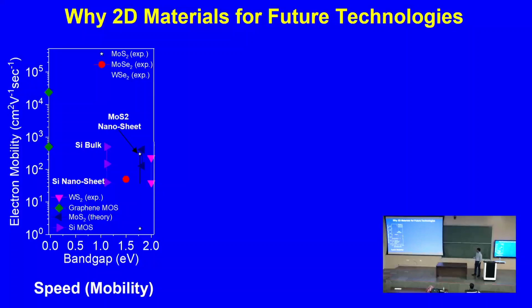Now if you compare the TMDs with silicon and other things, what you notice is that if you compare the TMD nanosheet with silicon nanosheet, the mobilities are far more superior. I am talking about nanosheets because, for example, if you have to build a next generation transistor which is better than FinFETs, you compare with FinFETs, you compare with nanosheets, right? So in FinFETs or in nanosheet transistors, what would be the typical silicon film thickness? Not more than 5 nanometers. So when we compare the mobility of MoS2, which is certainly less than 5 nanometers, versus a 5 nanometer or 10 nanometer thin sheet of silicon, you find that the mobilities are far more superior.